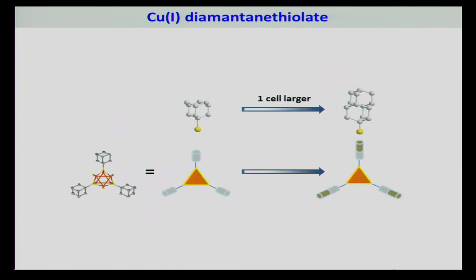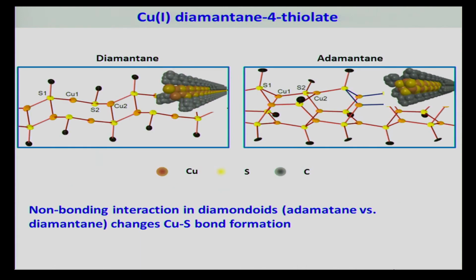Now comes the question, what happens if we change the adamantane to diamantane? Well, by naive thinking, which we originally had, you have a core shell structure to start with the adamantane. Now, diamantane is nothing more than just adding one more cage to the adamantane. And what we initially thought was that, okay, you still have the same structure with the same arrangement of copper and sulfur species, but you only have a thicker shell because of a larger diamondoid. And what we found really surprised us.